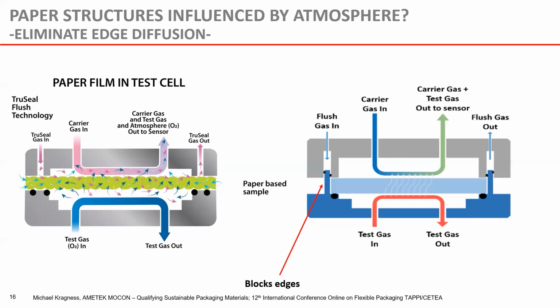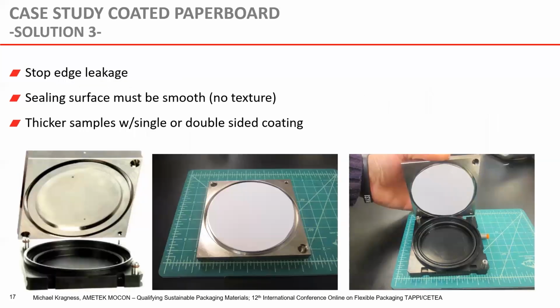So what we did was we came up with a cell that blocks your edges, as in this example on the right, where it has a dam over the edges of the paper sample, so you don't get any atmospheric influence. It seals the edges physically by having basically a fence around the perimeter of your material. And looking at these photos here, you see this cell that has a raised lip. So that actually blocks the edges from having any edge diffusion. And this works very well. It works well for thicker materials and some thin materials that have a good coating, either on one side or on both sides. But the sealing surface must be smooth, otherwise it's not going to seal properly.